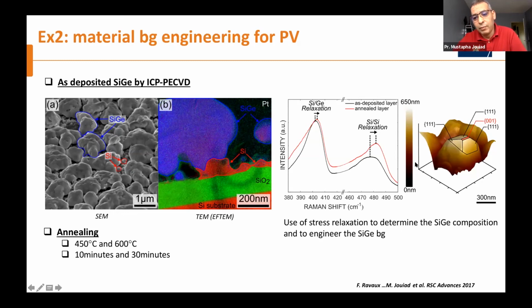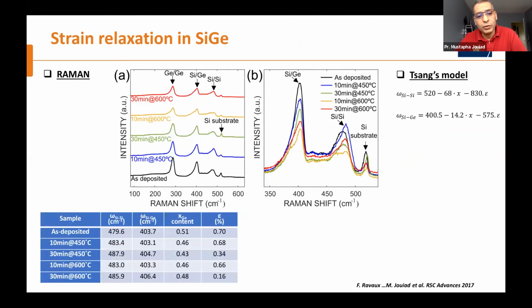So we were even able to reorient our grains, so they can be used, for example, like a waveguide. We didn't try that, but this is one of the possible applications of this composite. So basically, we did different heat treatments. It's rapid thermal annealing, which consists of annealing only the top film without damaging the substrate. And we did it at different times and different temperatures, and this led to different stress.